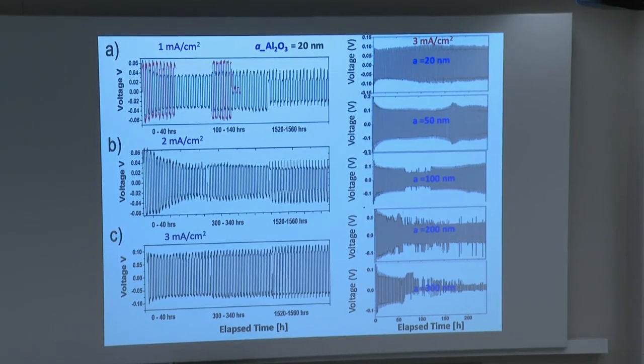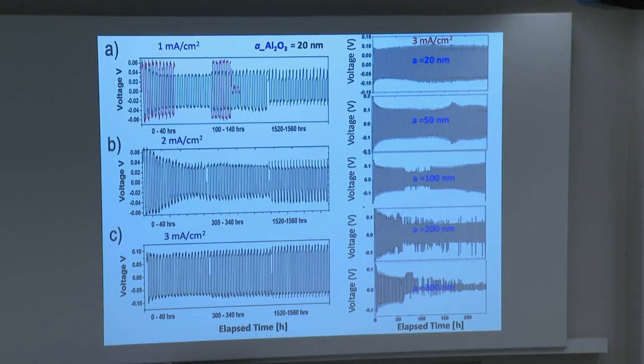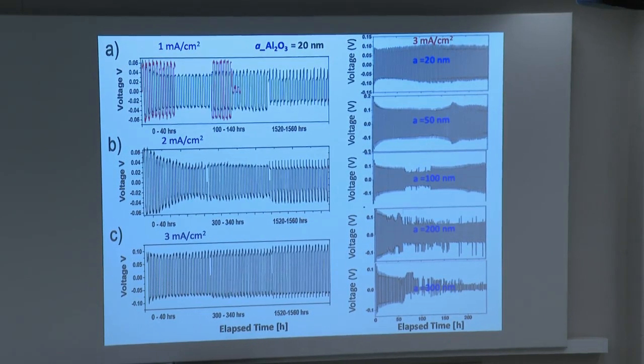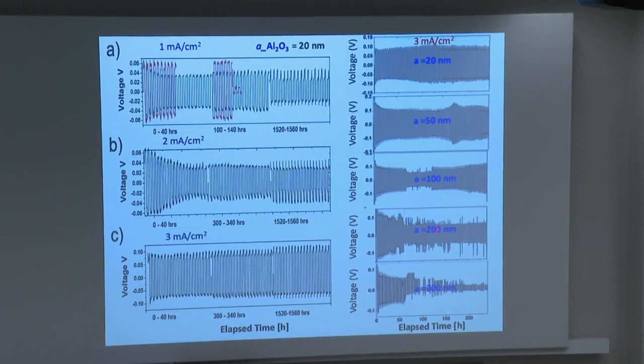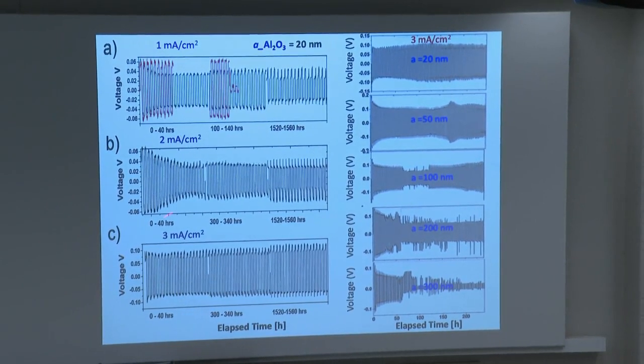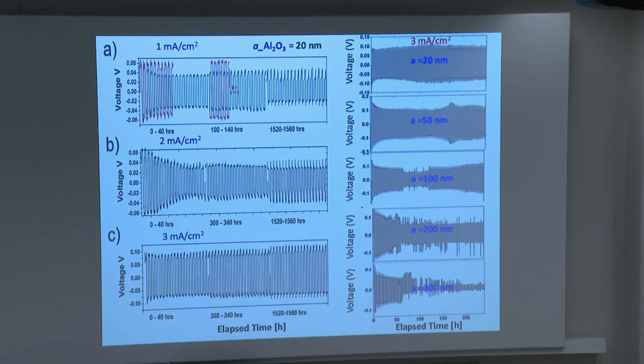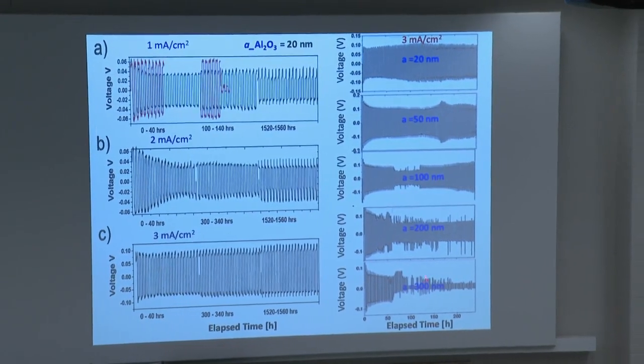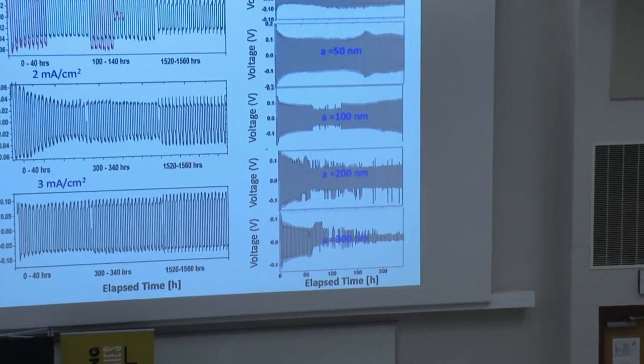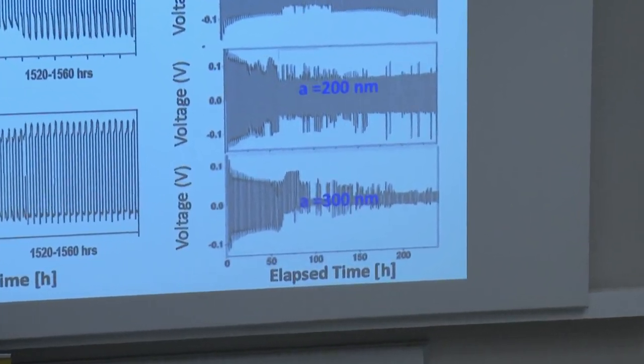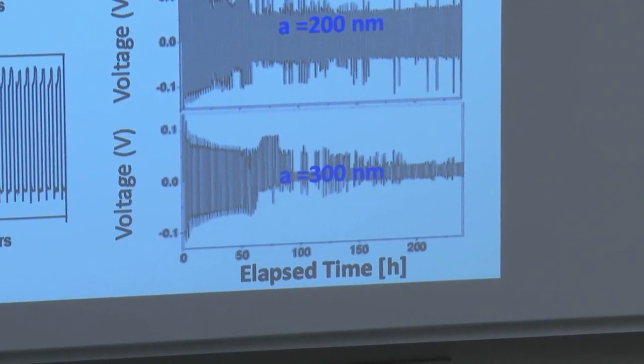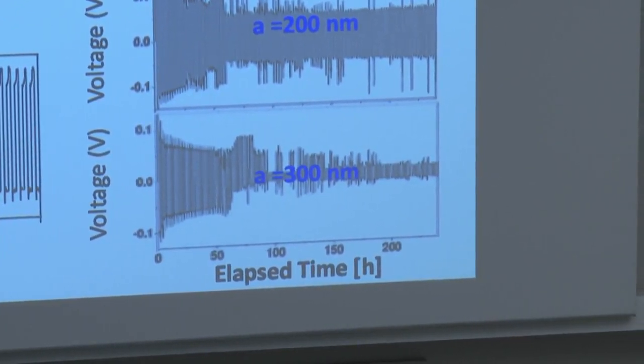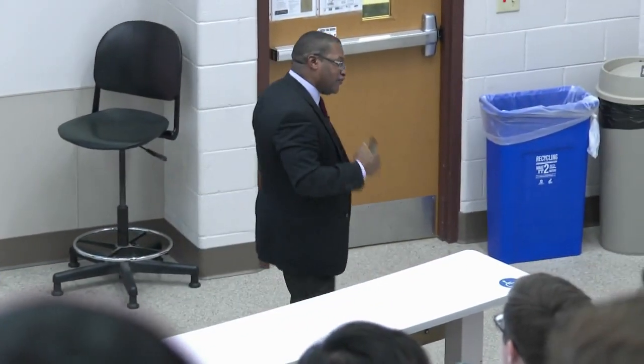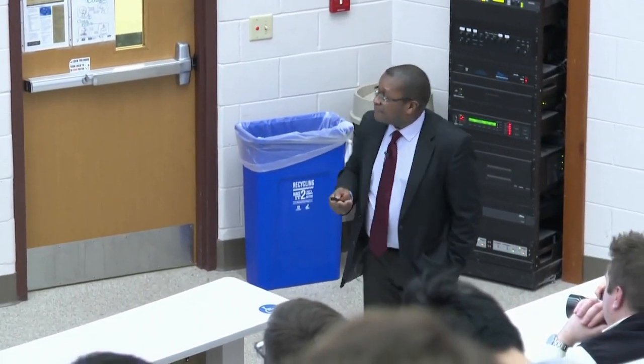So the question was, okay, 20 nanometers is a lot smaller than 250. What happens as you begin to approach the limit specified by theory? So we started to look at bigger and bigger AAO structures, so 20, 50, 100, 200, 300, and for each of them we're looking at the highest current density. And I think what you will notice here is that somewhere between 200 and 300, things went awry, which is just remarkably consistent with the theory. In fact, I don't believe this to be true, just so you know, all right? But it is true, at least in this instance, that it's almost right on the money, telling us that the cutoff length scale is consistent with what we predicted theoretically.